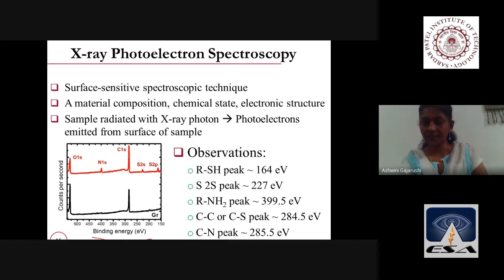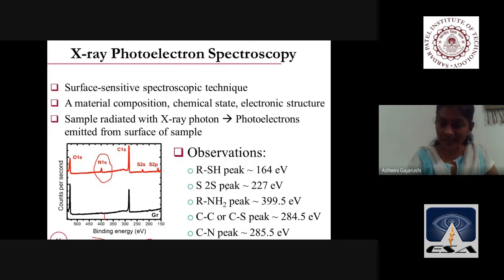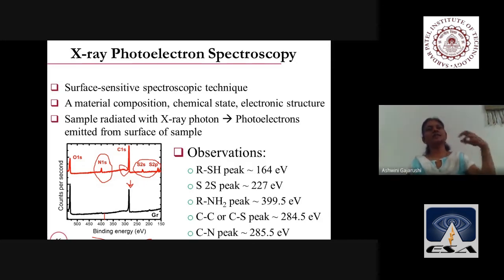So for graphene, there is no peak around 400 or 399 electron volt. But for this, an N1s peak has occurred at 399 electron volt. This peak corresponds to the NH2 group. Then there are two peaks corresponding to sulfur, the S2s and S2p peaks, at 227 and 164. They were not there before for the graphene. Similarly, a C-N peak has also appeared, this peak. It was not there earlier. Then the C1s peak has become pronounced. So all this shows that the graphene has been modified with a material which has sulfur attached to it, which has an NH2 group attached to it.